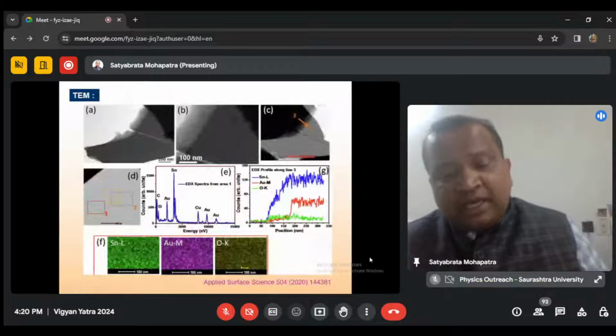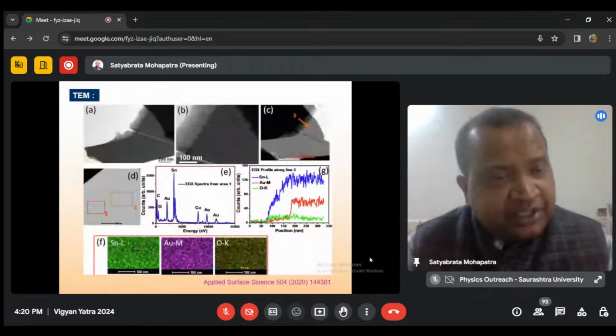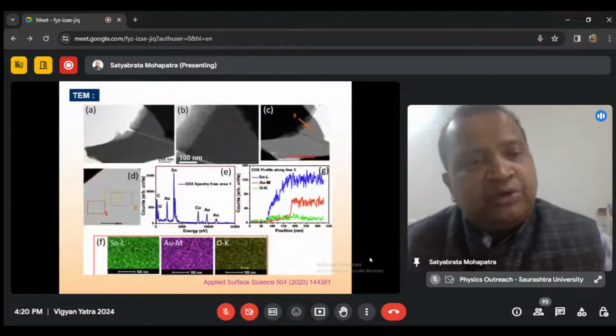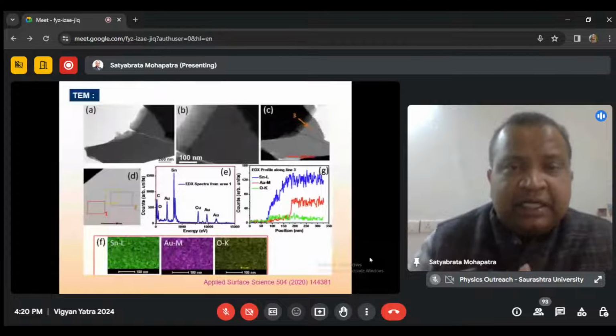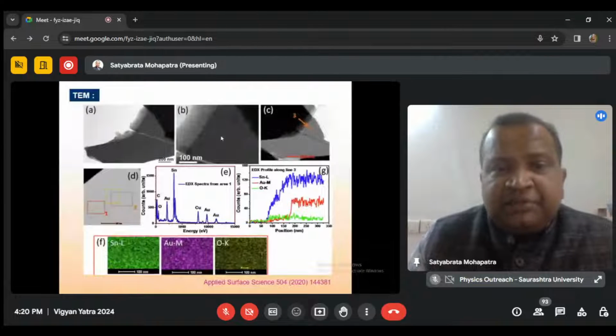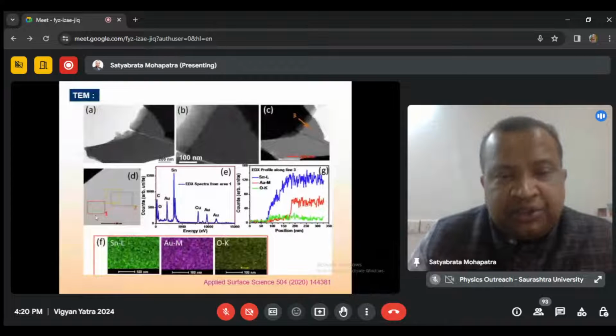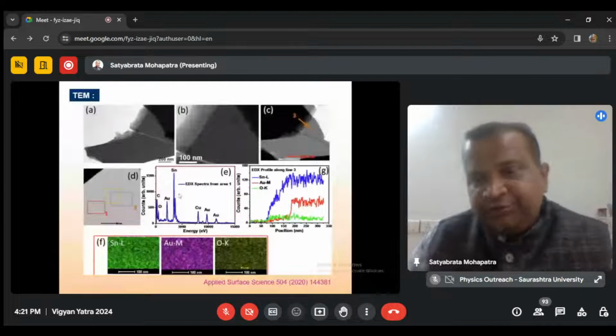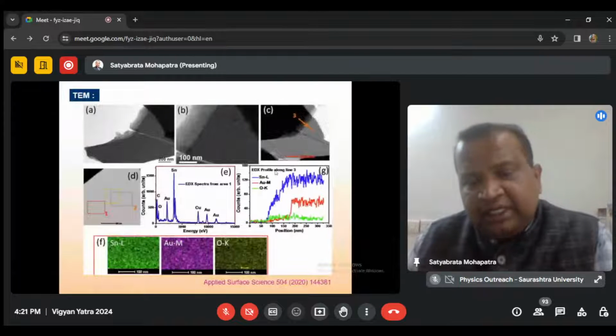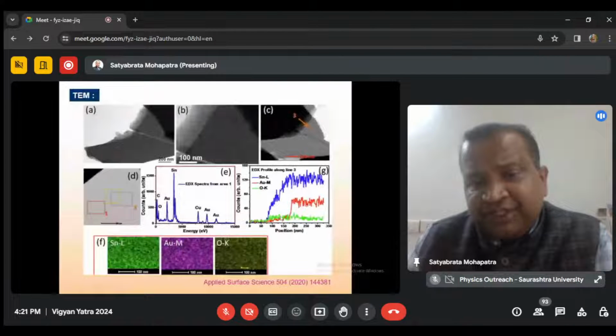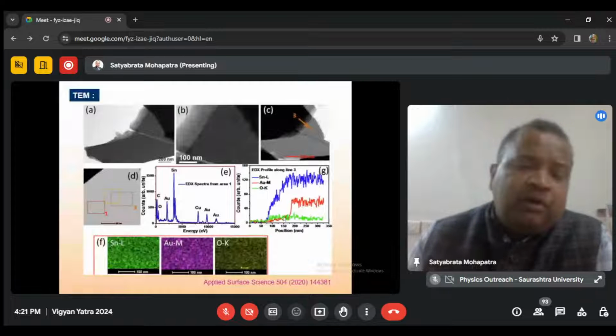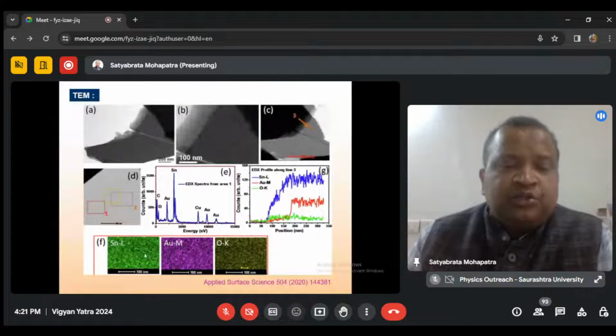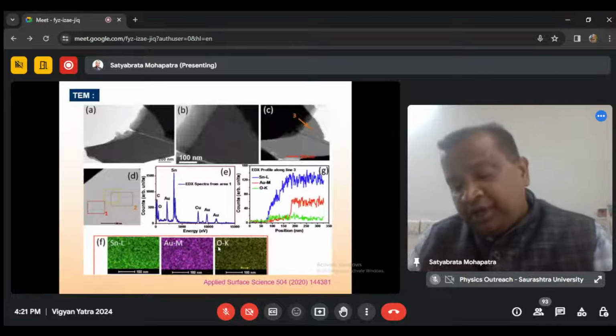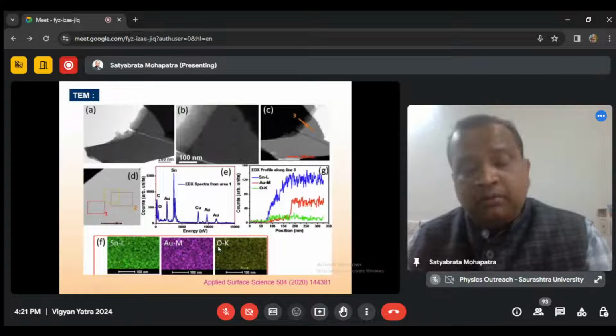So to look further, we went for cross-sectional transmission electron microscopy, and in B you can see these particles of gold on a tin oxide film. Then we went for rigorous analysis with EDAX, which shows the variations of tin, gold, and oxygen across this film. So it clearly shows that this is a gold tin oxide hybrid film.